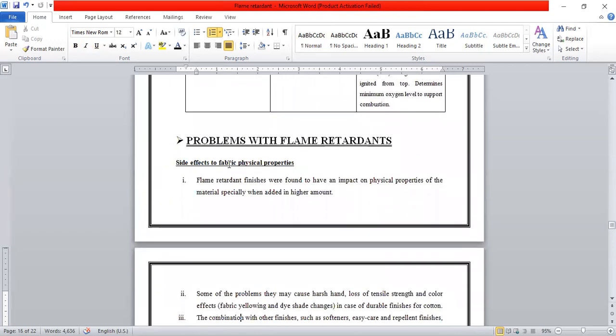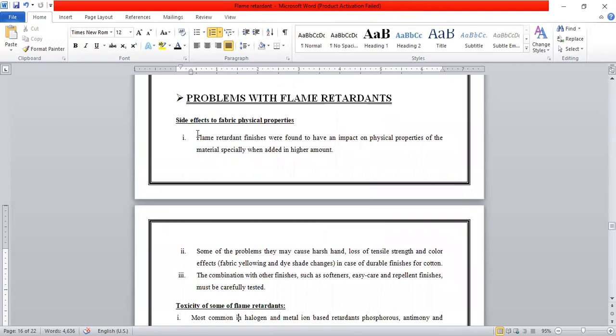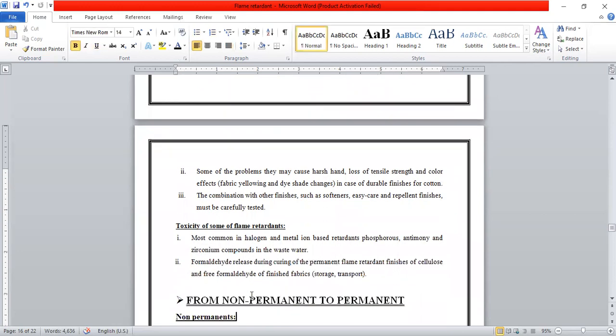Problems with flame retardants: side effects to fabric physical properties and toxicity of some flame retardants. First one is side effects. Flame retardant finishes were found to have an impact on physical properties of material, especially when added in higher amounts. Some of the problems: they may cause harsh hand, loss of tensile strength, and color effects, fabric yellowing, and dye shade changes in case of durable finishes for cotton. The combination with other finishes such as softeners, easy care, and repellent finishes must be carefully tested.